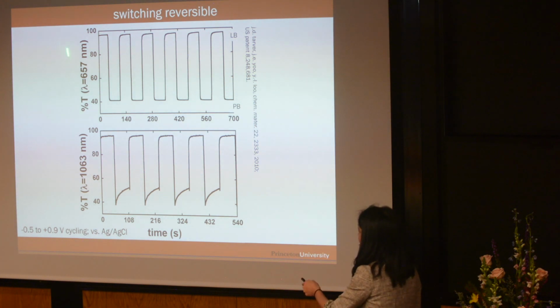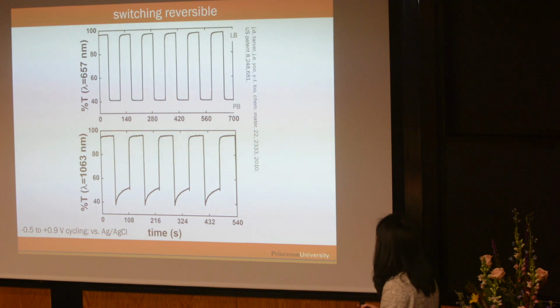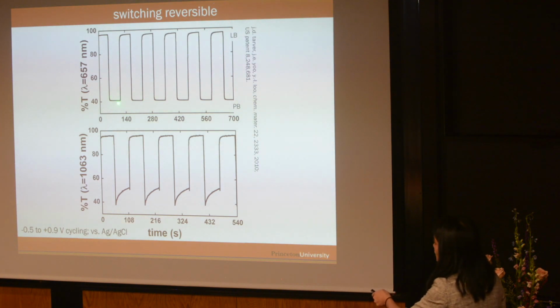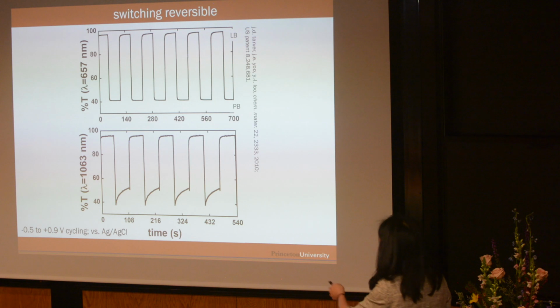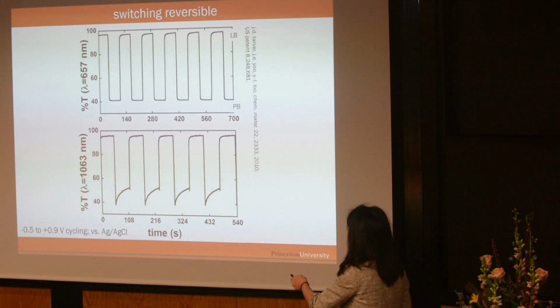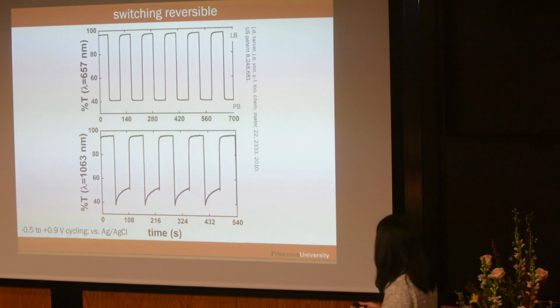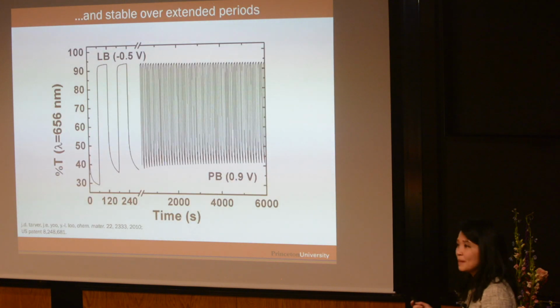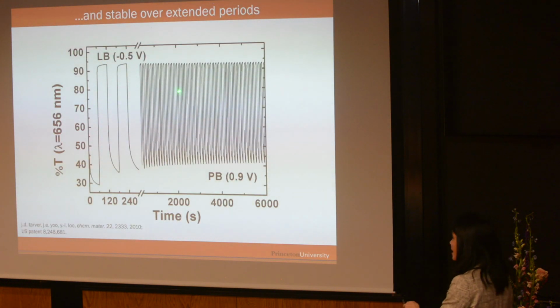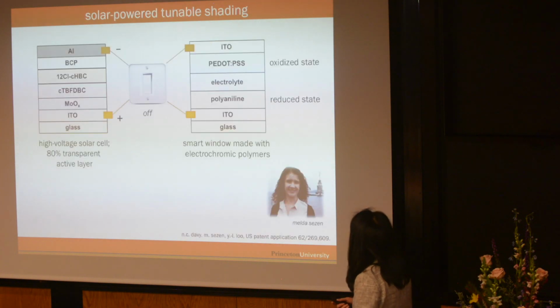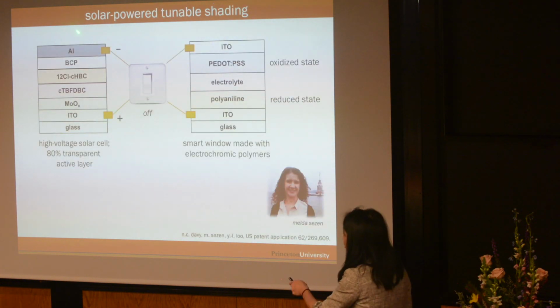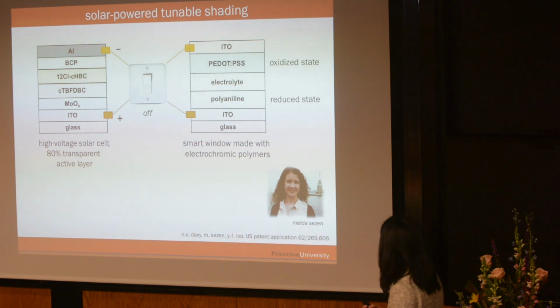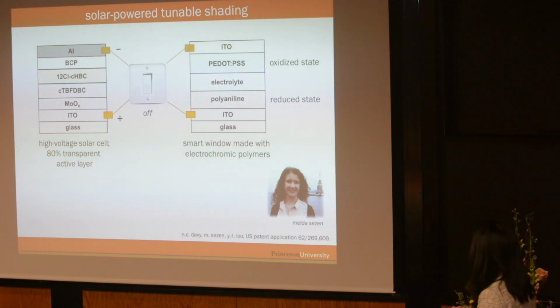I'm plotting percent transmittance. This is in the visible, and percent transmittance in the near infrared. And you can see nice contrast, right? 40% to almost 100%. So this is very transparent, and then this is very dark, both in the visible and in the near infrared. We can cycle this back and forth, back and forth, back and forth. It's very stable. And so the idea, again, is to couple our transparent solar cell with one of these electrochromic windows. And so the makeup of our electrochromic window is as follows.